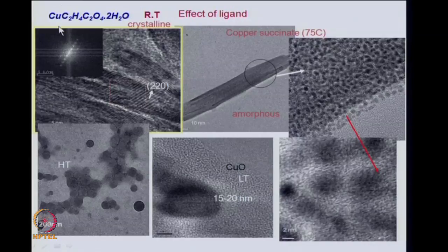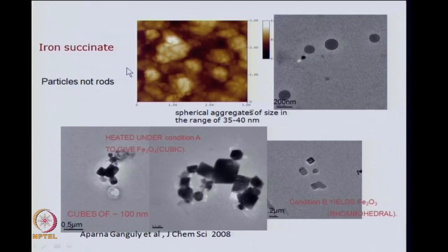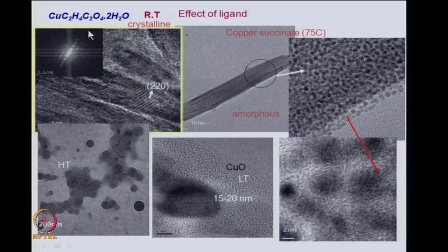Here we see that this is copper succinate. In this case, depending on the ligand, we can get crystalline anisotropic structures under certain cases, and you can change them to amorphous structures, and that amorphous structure can again give rise to particles like this, and on heating can give rise to the oxides. So, this is iron succinate, where trivalent iron was used, so trivalent iron was not giving any rods, whereas divalent copper gave us anisotropic rods with succinate ion also. At room temperature, they are crystalline rods as you can see from the transmission electron microscope, and if you heat it, it becomes amorphous.